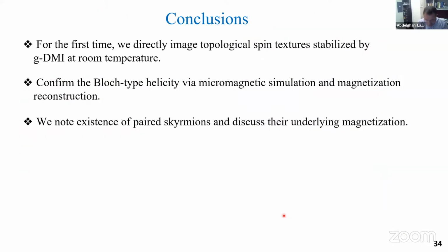So just, I'm exactly in time, to summarize this talk. In principle, this is the first measurement of topological spin texture stabilized by the gradient DMI at room temperature. We also confirm the block type helicity. This is expected in bulk DMI materials. The only difference here is a gradient bulk DMI. Also, we found the formation of paired skyrmions, and we think it's related to the skyrmion anti-skyrmion interactions.